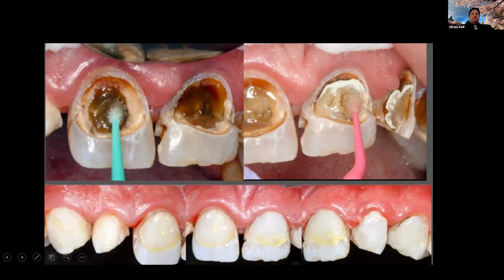As you can see, there is a little bit of yellowness around the margins here, which is, I think, because of the precipitate that potassium iodide creates with SDF. But this is, in general, a way better appearance than having applied silver diamine fluoride without potassium iodide. There is one thing I want to recommend here. If you have to use silver diamine fluoride because of its advantages in terms of antibacterial and remineralization effects, and it's an anterior tooth, it's best to use a conventional Glassionomer.